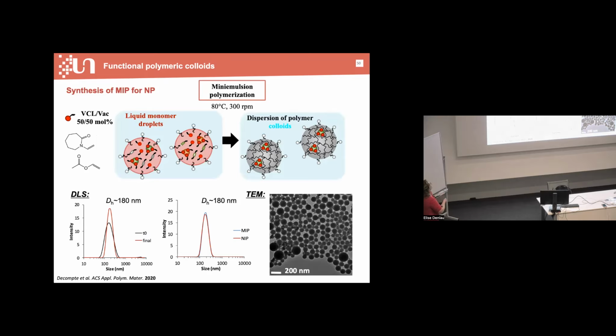So we use the mini emulsion polymerization of vinyl caprolactam and vinyl acetate. And we form very well-defined molecularly imprinted microgels, and also non-imprinted microgels, meaning in the absence of the template molecule, in order to assess the selectivity afterwards. What we first characterize is the size of either the colloid with the imprint, the MIP, and the colloid without the imprint, the NIP, non-imprinted. And we found that the microgels exhibit exactly the same size. And we could see on this picture that the dispersity is quite low.